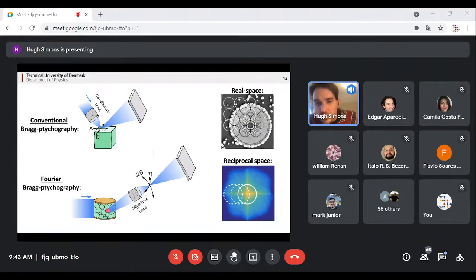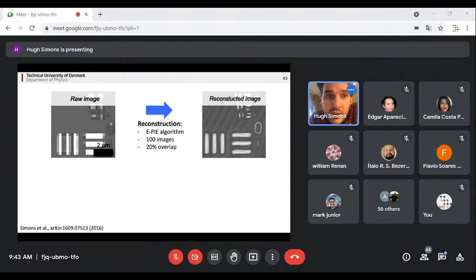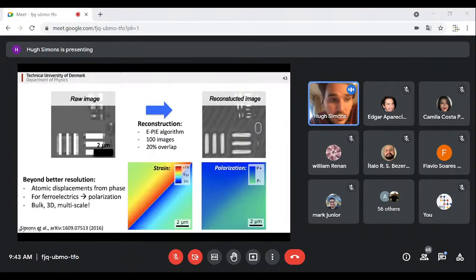So this sounds very hand-wavy, and I'm sorry it is for the moment, because this is still very much a work in progress. But we're very excited because it gives us a method not just to improve the spatial resolution, but also to really separate the amplitude and the phase. What we've tested so far, we've been able to improve the spatial resolution quite significantly. We've also been able to measure the phase.